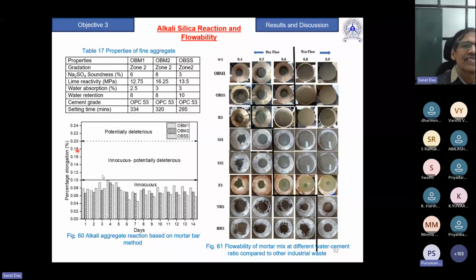Flowability: if you see OB sand, even at 0.6 it is not becoming flowable compared to standard sand. Standard sand at 0.6 you see is able to flow. Standard sand 1, standard sand 2. With ferrochrome slag also I am able to get flow. River sand you see has more flow. So this is becoming a dry flow with 0.6% water content. So these aspects you need to study when you are going to use it for mortar or concrete.